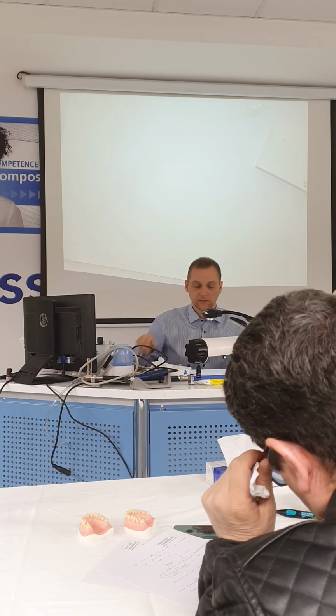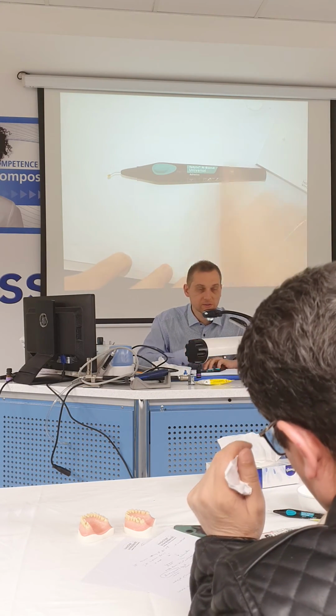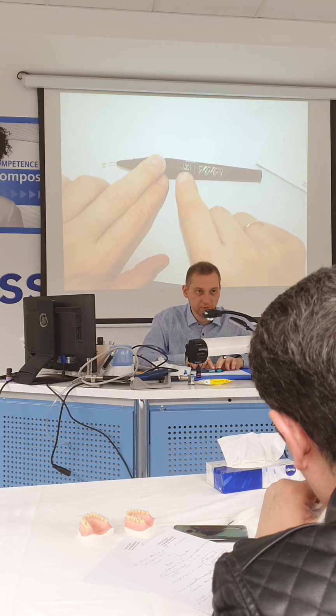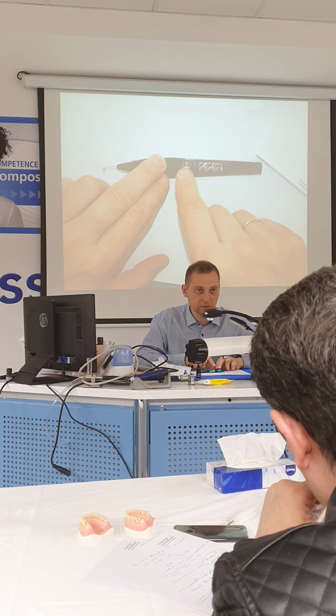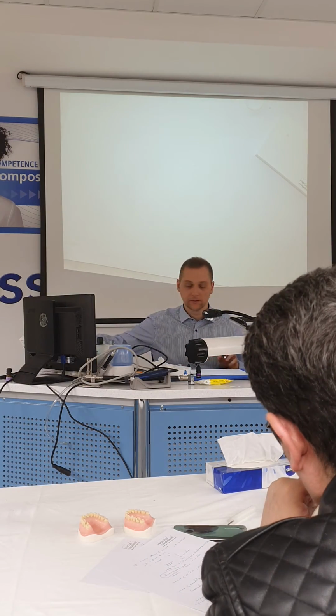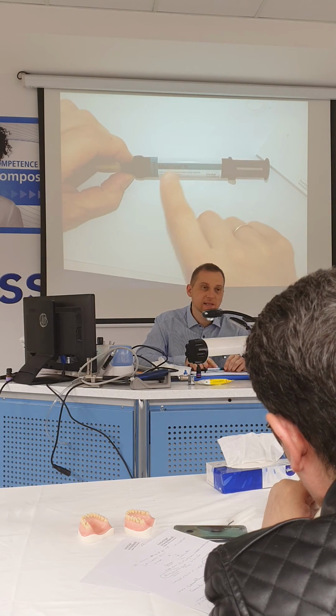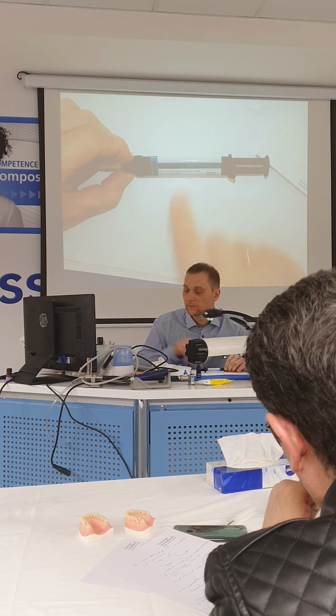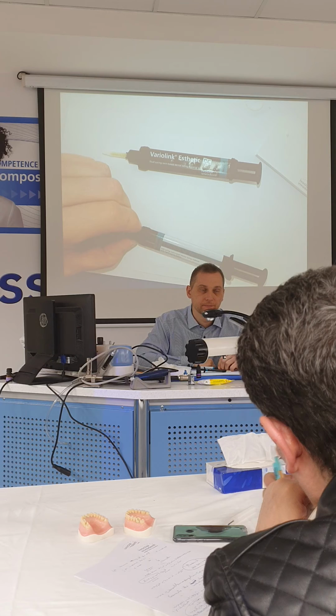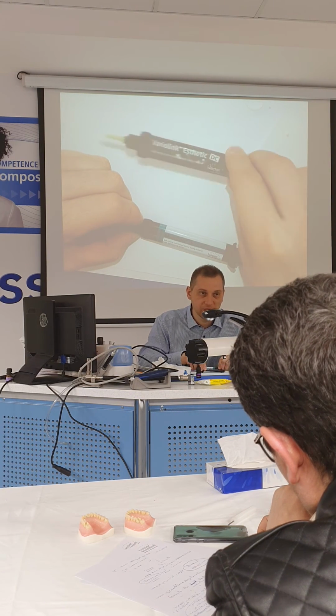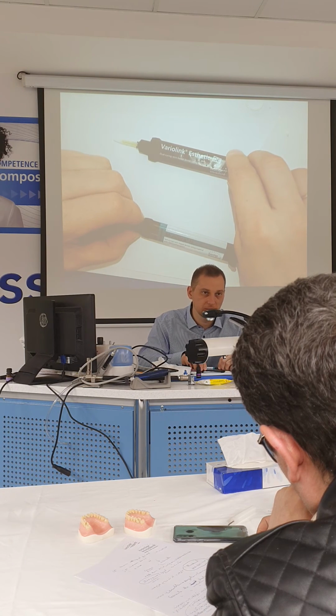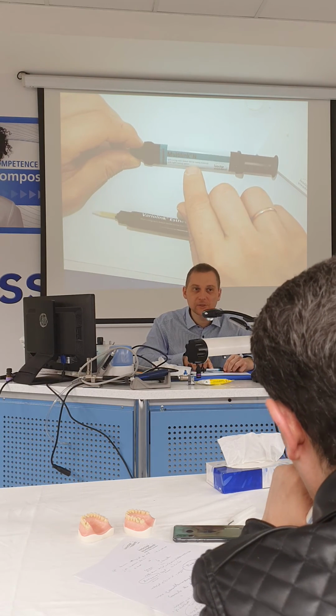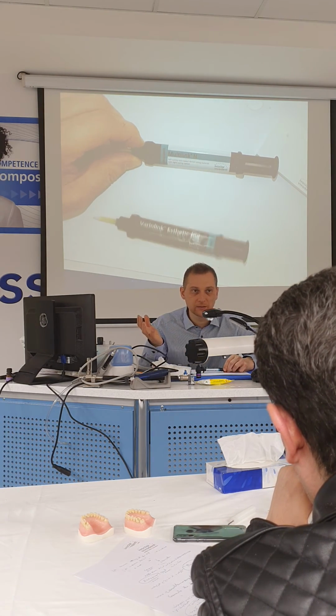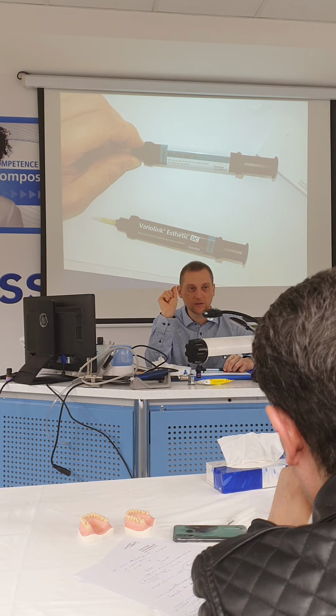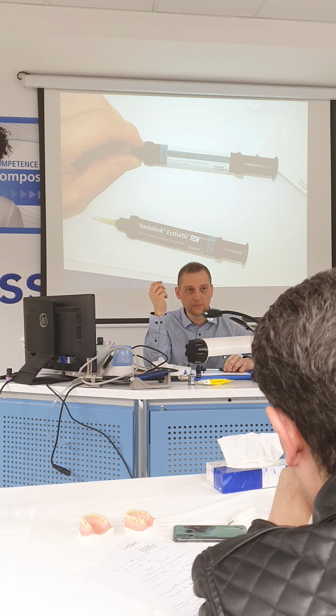With Variolink Esthetic, this adhesive comes in the kit. It is also self-etching, but it can be used with phosphoric acid in advance. And for the veneers, it is recommended to use phosphoric acid first. This is the first reason. The second reason is that Multilink N still has amines in the composition. Variolink Esthetic is amine free. That's why Variolink Esthetic has better shade stability. It will never change its color with time. This one will slightly change the color when you have exposure to sunlight. And the veneers, in front of the smile, veneers are thin, so you'll get this exposure. Okay. This is the reason.